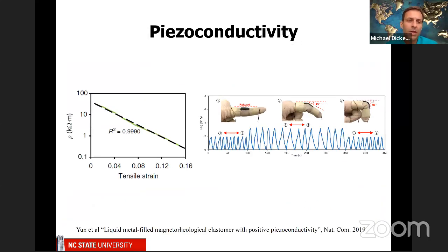And this is just an example where the researchers here measured the resistivity versus strain. And you'll see that the resistivity goes way down. This is orders of magnitude change, two or three orders of magnitude change over 10% strain. So this is very, very sensitive. So one of the consequences of this, and there's millions of ways to make strain sensors, but you can put this, for example, on a soft material and you can change the resistance as you deform it. And the cool thing here is that this is on a log scale. So here's at rest, you bend your finger and it goes up by 100. So it's actually a really big change in your signal.